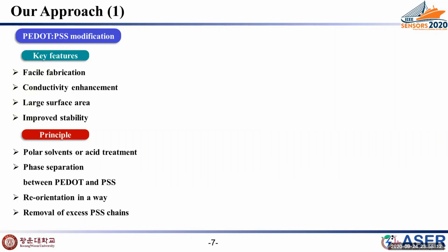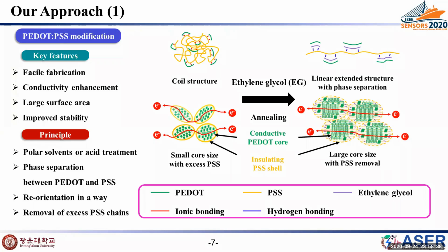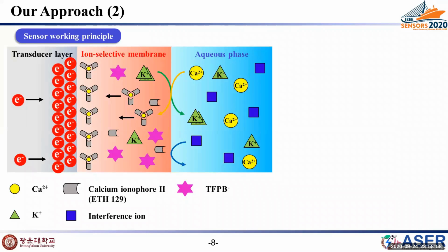And it is our approach. PEDOT:PSS can be modified by simple treatment with polar solvents or acid. It has been found these treatments result in conductivity enhancement, larger surface area, and improved stability by phase separation, crystal reorientation, and excess PSS removal. For easy fabrication and safety, we used ethylene glycol, EG, as a co-solvent of the PEDOT:PSS water dispersion. This method changed the coil-like structure and small PEDOT core size to a linearly expanded structure and large core size with excess PSS removal.